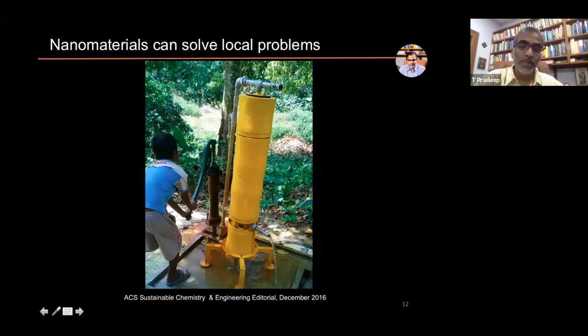And when this boy makes one stroke of this pump, water from about 50 to 80 feet comes up, and you get about 300 ml of water in one stroke. And that water is often contaminated with iron in this region, and that is why the cemented platform is red in color due to iron oxide. And it also tells you that there can be arsenic in it, and this particular pump delivers arsenic to the extent of something like 80 ppb to about 120 parts per billion.